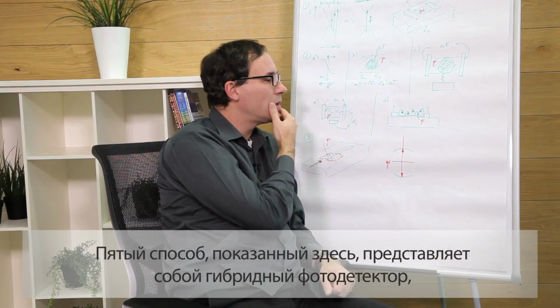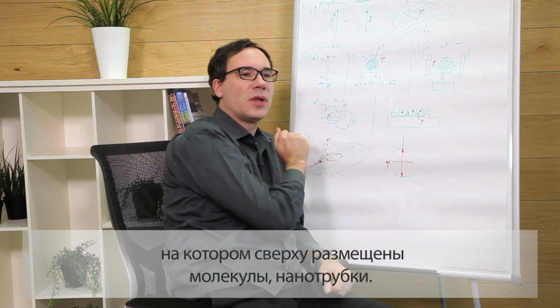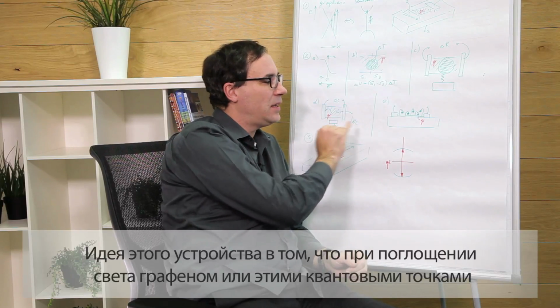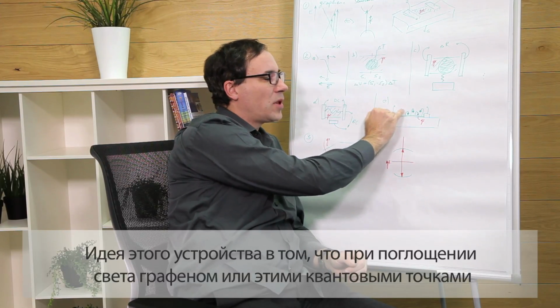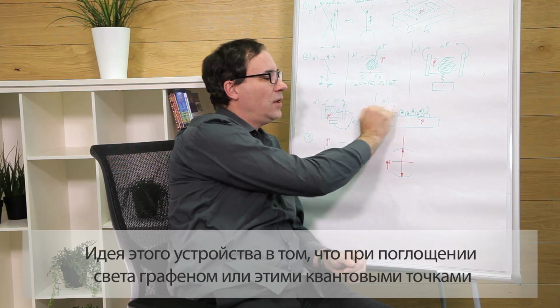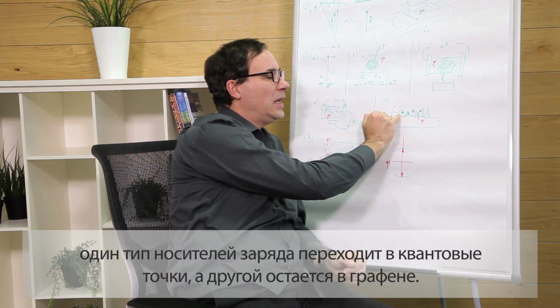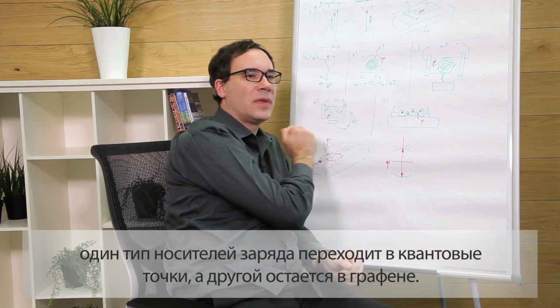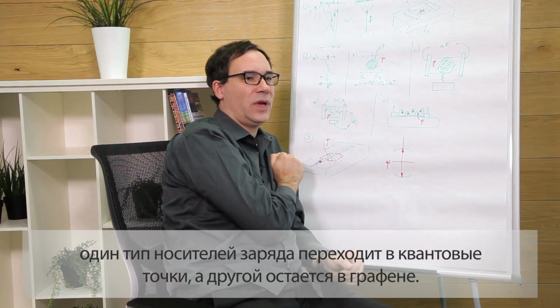Now the fifth method is actually shown here. It's a kind of hybrid photodetector, where you have a standard graphene photodetector, a graphene sheet, and on top of the graphene sheet you put some molecules, nanowires, whatever you want. The idea of this device is that you absorb the light, for example, in graphene or in those quantum dots, and you transfer one type of carrier into the dots, and the other type of carrier remains in the graphene.